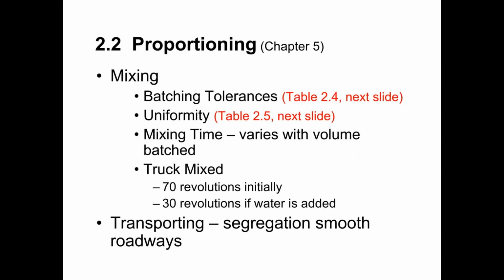Mixing time is generally going to vary with the volume of the concrete that's being produced. Over on page 217, there are some rules of thumb for how long a batch of concrete should be mixed. These are rules of thumb. Keep in mind that the mixing time is going to vary, not only with the volume of the concrete, but also with the type of mixer that's being used.